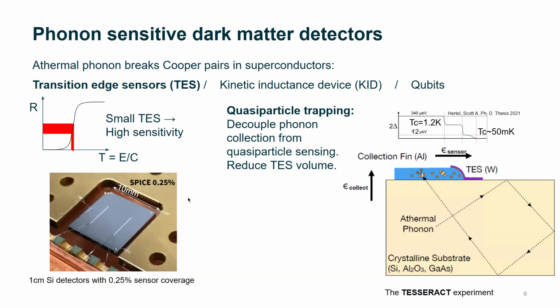Not only do we reduce the area, we also use the technique called quasi-particle trapping. So here, on the right, this is a demonstration. First, we let the athermal phonon propagate, bouncing around in the chip until it hits our device, our sensor. And our sensor actually has two components. First, there is a large area phonon collection fin, and it's made of aluminum. It's directly coupled in good contact with the actual TES, which is tungsten. And the tungsten is much smaller in volume and thinner as well.